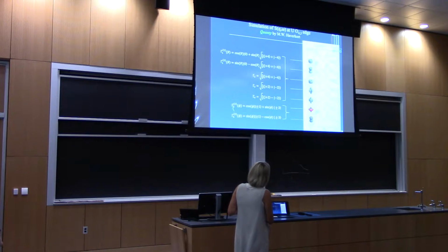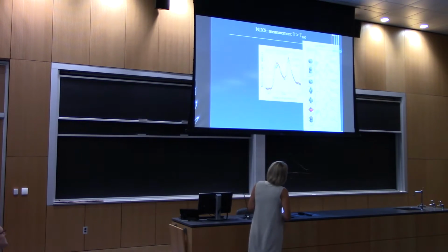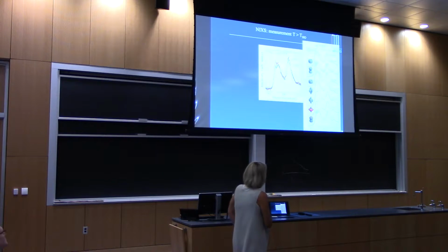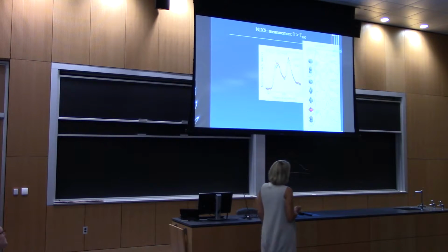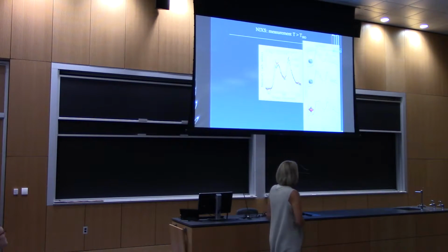And the same here is for the gamma 5, where I show you the biggest contrast, here for the gamma 5 plus minus 3. If I would mix in some of the JZ1, I would go via 0 to this type of patterns. And now we compare this with our spectrum. This is the measured spectrum I showed you before. This is the simulation. And I think if I compare simply red over blue, and I compare it with this, I can eliminate at once many, many spectra. I have only 3 left. The gamma 1, 90 degrees, the gamma 2, the gamma 5. In this extreme case where I have almost a plus minus 3 without any 0 mixed in.